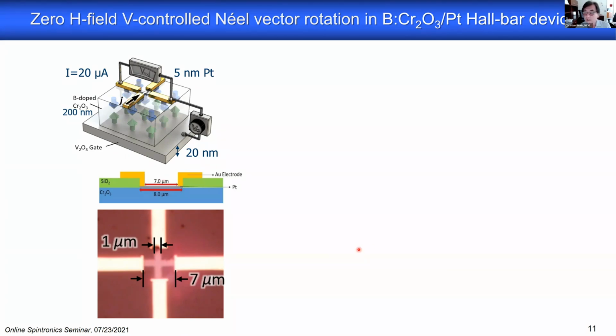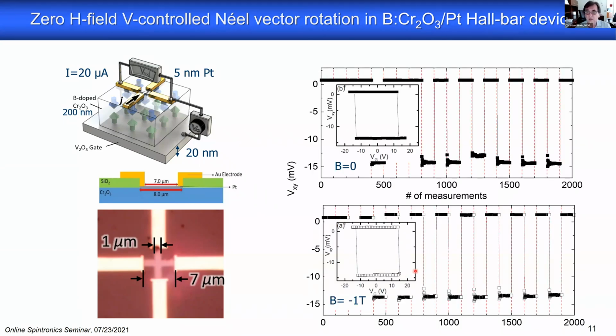And now I show you the interesting results. So maybe we start with the bottom here. You see an inset. The inset basically tells you that we changed the electric field and that we could reach threshold electric fields where we switched from one state to the other. And here we had a magnetic field applied. Why? Because I told my postdoc, apply a magnetic field, because the only reason why the system should ever switch is the magnetoelectric effect. And without a magnetic field, you will not observe a switching. So he did that. He observed the switching.